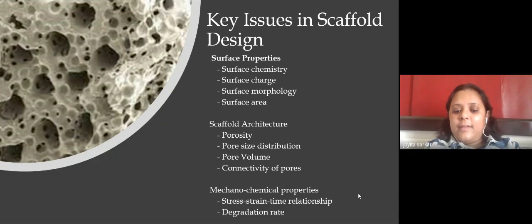And it is very interesting that if you design a scaffold which mimics the compressive moduli of the different stages of liver disease, and you try to grow hepatocytes on that, you will find the hepatocytes are more functional if they are grown on the scaffold that mimics the compressive moduli of normal liver. And the functionality decreases as you go to the fibrotic and cirrhotic compressive moduli. But if you want to differentiate the stem cells into hepatocytes, then a fibrotic and cirrhotic compressive moduli will be more helpful, because for the liver stem cells, the increase in the compressive moduli is actually a signal for the stem cell to differentiate into hepatocyte and rescue the organ from the disease.